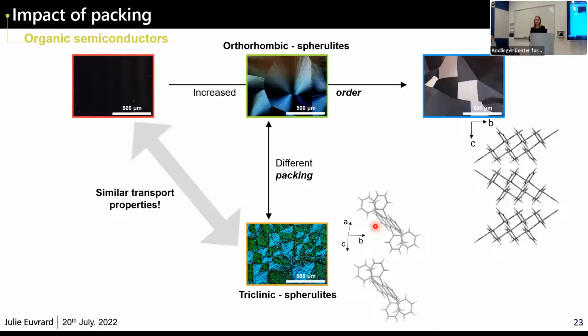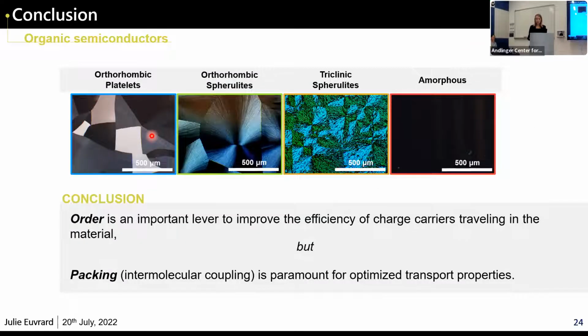So that means that even though, I should mention that the triclinic phase is not a super ordered phase, it's still more ordered than the amorphous film. And still, there is no improvement in transport properties. So overall, what do we conclude? We conclude that sure, order is important, and we see that by increasing order, for example, by increasing order inside a grain, we can dramatically improve the transport properties. But it's not sufficient because we have also increased order in this triclinic film, but we have not improved transport properties at all. That's because the packing is totally inappropriate. So if you want to really design the ideal molecule, you need to design a molecule that will interact with each other and pack in the solid phase in a way that is appropriate for electrons and holes to travel around.